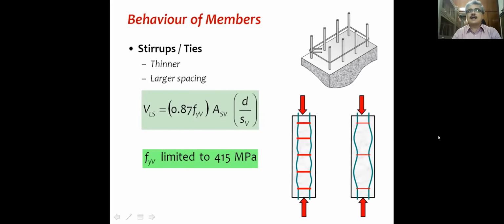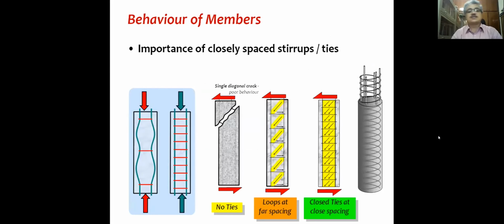And that is going to continue now. So probably there is not so much of an incentive to go and use higher grades of steel, particularly for transverse reinforcements, because that is not something that is warranted, that is desirable. Thin stirrups at larger spacing is not good for structural reinforced concrete and prestressed concrete members. So that is not something that the code is likely to allow.